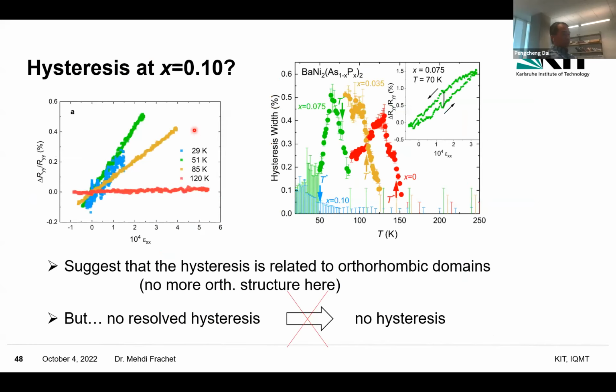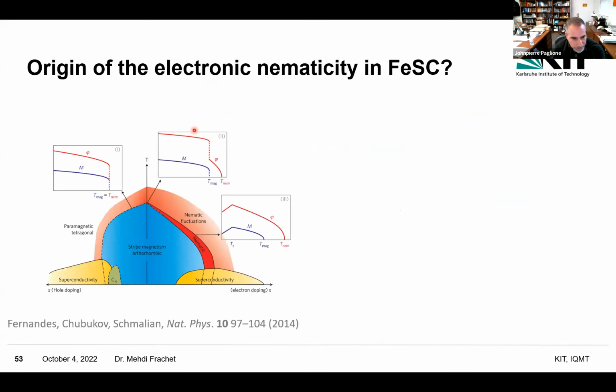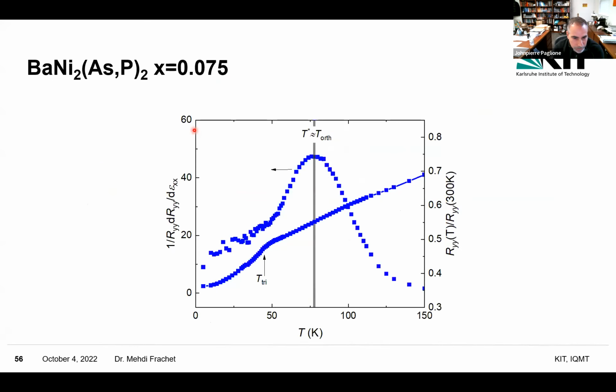From our side, it makes me want to redo the measurement again, but we did it many times. So I'm just showing you now what we got at 7.5%. You see the resistance, which is measured on the piezo, and this downturn is really the transition, and the maximum of the elastoresistance is close to 80 Kelvin. So when you increase phosphorus doping, the difference is really larger, about 30 Kelvin. What would be interesting is to have a look at this orthorhombic distortion in the highly phosphorus-doped sample close to the suppression of the triclinic phase. That would be something interesting, if there is any.